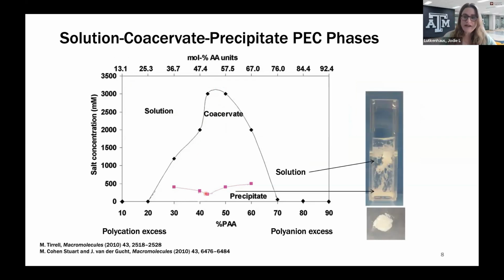The last phase is the one that we work with the most in my group. It's the solid-like precipitate. It tends to appear in conditions of very low salt concentration. The complex can be feathery, very disorganized and ugly looking, and it's solid-like, and you can isolate it by centrifuging, and then we can dry it down and grind it into a powder for further characterization.